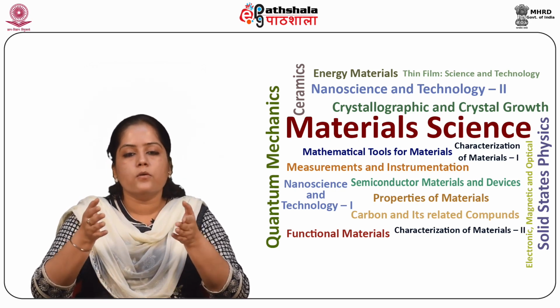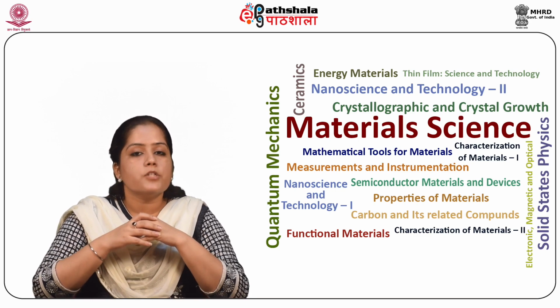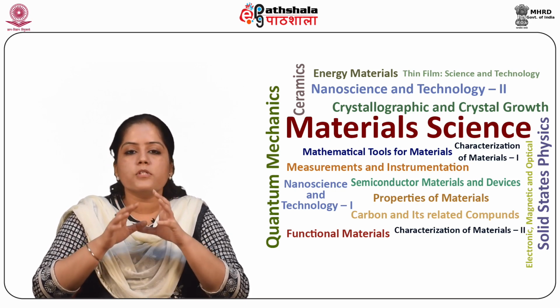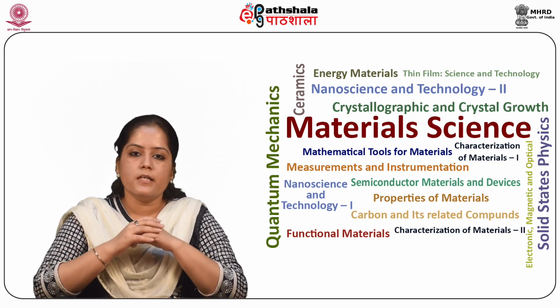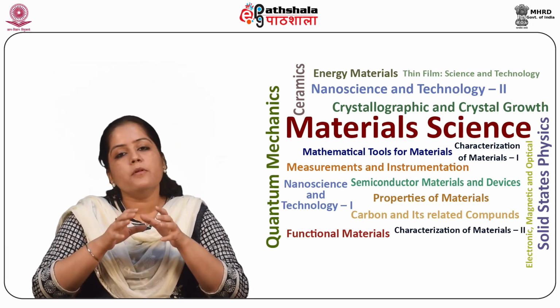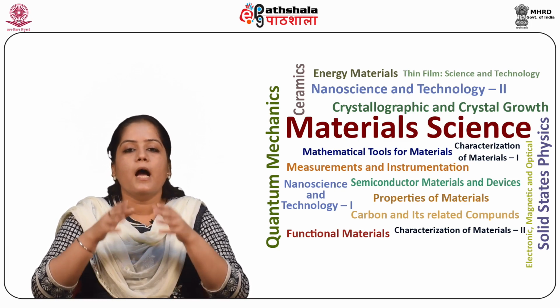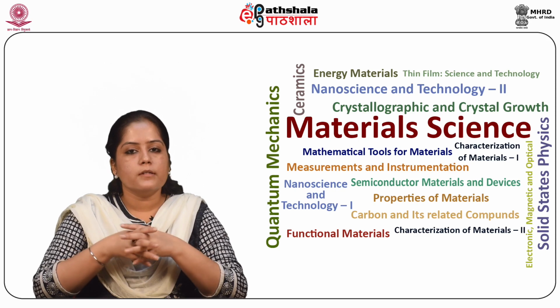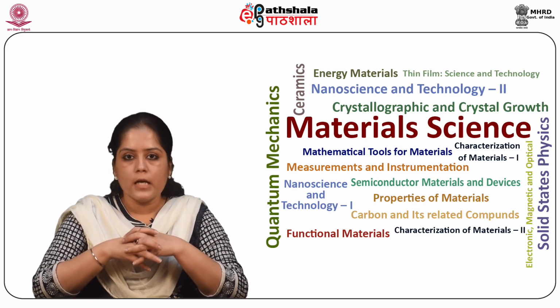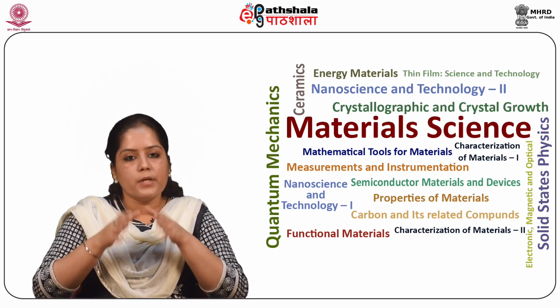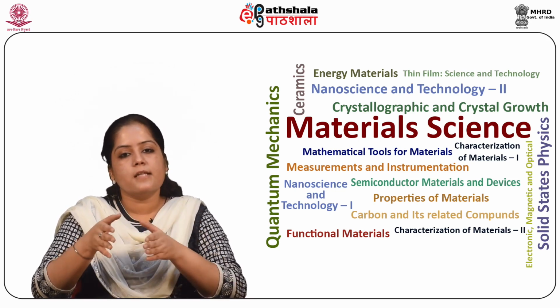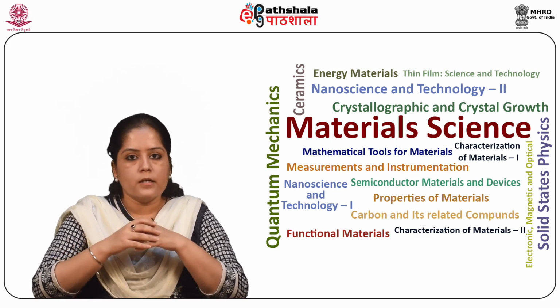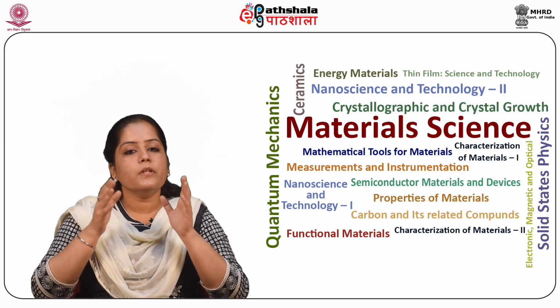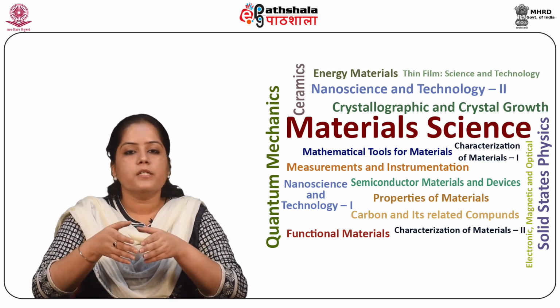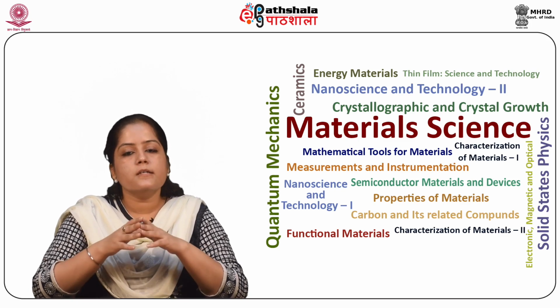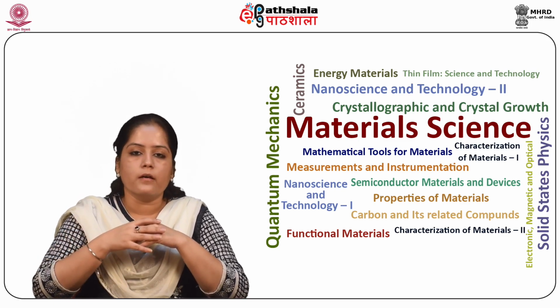Many ceramics can undergo transformation toughening. Transformation toughening is the most pronounced and most well studied in zirconia. The stable phase in zirconia is monoclinic at room temperature. However, the high temperature tetragonal phase can be stabilized at room temperature if, first, the particle size is less than a critical size. Second, a stabilizing additive like Y2O3 has been alloyed with ZrO2. So the critical size is increased by alloying.